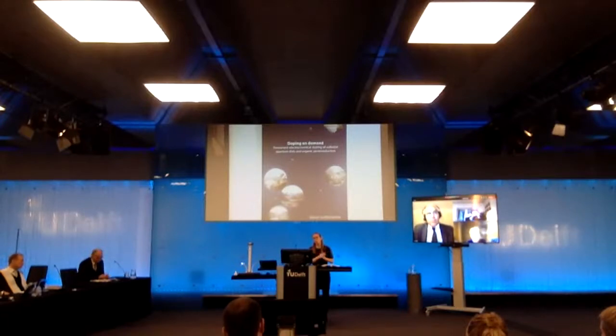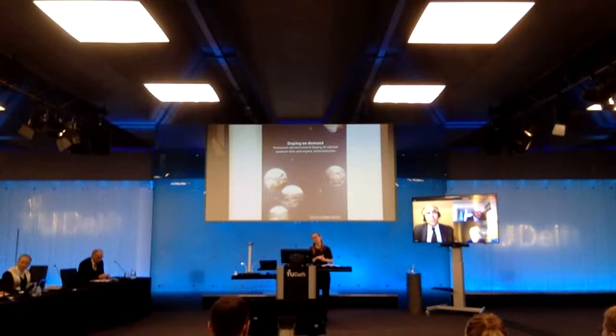But we have also seen the instability of cadmium selenide, and we have seen that by putting shells around it, you can get very nice reversible electrochemical measurements. For example, a cadmium sulfide, zinc sulfide shell, a little bit thicker cadmium sulfide and a little bit thinner zinc sulfide shell. You can really have very beautiful electrochemical data if you place those additional shells around it.